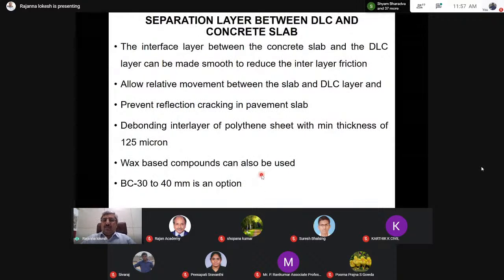In the initial first slide, I was mentioning the separation membrane. Separation membrane can be either a polyethylene membrane or a bituminous concrete of 30 mm or 40 mm, or even a wax-based compound can also be treated as a debonding layer or separation membrane. The interface between the concrete slab and the dry-lean concrete is to be provided as smooth to reduce inter-layer friction and allow the relative movement of slab and DLC layer, preventing the pavement from reflecting cracks in the slabs. Debonding interlayer can be 125 micron polyethylene sheet.